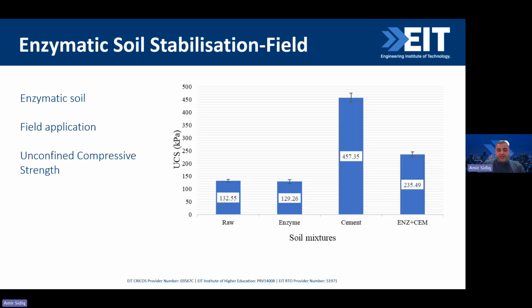Use of the unconfined compressive strength. We have the raw. The enzyme is slightly lower, but again, depending on the soil, because it's a non-homogeneous material, we cannot really say this is the 100% effect. It's slightly lower, but it's only about 2-3 kPa. Cement, of course, when adding cement, it actually increases the strength significantly because of the properties of the cement.